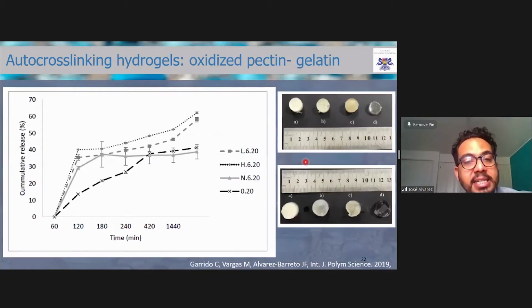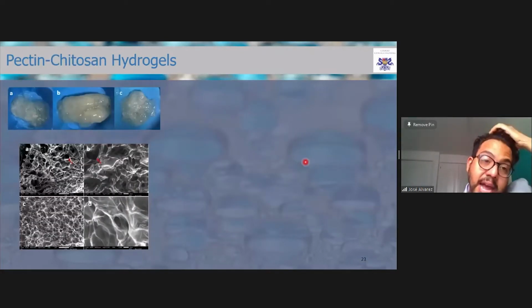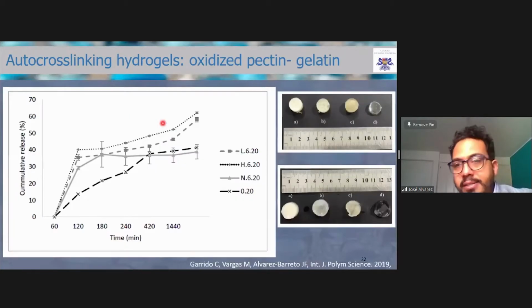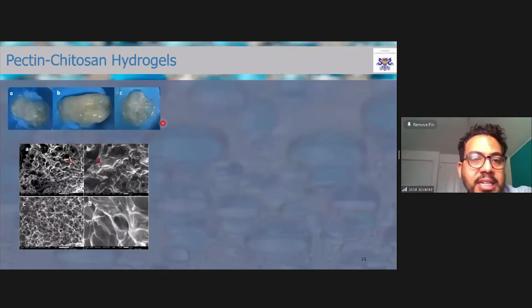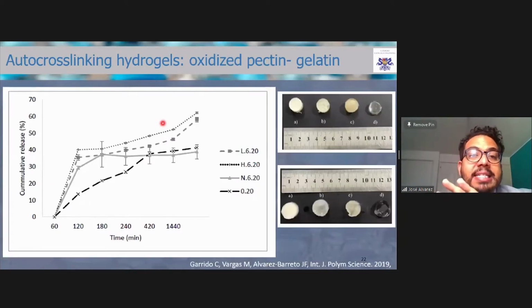Then we looked at pectin, but now with chitosan. You know, gelatin has some amine groups, but chitosan has a lot of amine groups, and we created these hydrogels with chitosan. You can see here the hydrogels, to our surprise, didn't look as compact as the ones with gelatin. However, they were way more stable. The gelatin pectin hydrogels were stable only up to 32 degrees, which means I could not put it in the body. I could use it for transdermal delivery, like skin patches, but not for internal applications. These were stable at 37 degrees Celsius.